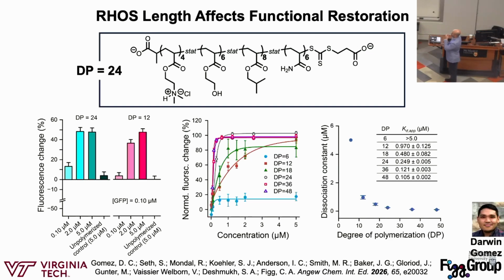One other thing that I think is really interesting and important to point out on this slide: we're looking at effective length, which I'll get to over here. But if we look at the GFP concentration at 100 nanomolar, if we add in 1-to-1 equivalents of our random heteroligomer to our GFP, we're still getting a fluorescence increase. There are a lot of different sequences and a lot of different compositions that we're adding. And even at a 1-to-1 polymer to GFP ratio, a lot of those polymers are interacting with the GFP surface and increasing fluorescence. So this is suggesting to us, for the binding that we're targeting, we don't need sequence precision to still see a functional output.